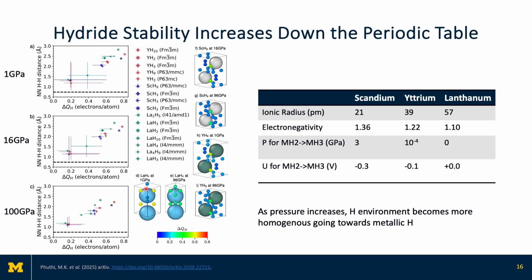Yeah, thank you. Just to follow up, the trihydrides are notably substoichiometric, and that's been known at low pressure for many, many years. There's a huge change in electronic properties as a function of hydrogen between YH2 and YH3, for example. You can tune that and actually measure that stoichiometry at low pressure using various techniques. It's harder at higher pressure, but at low pressure, it works pretty well. So good point.